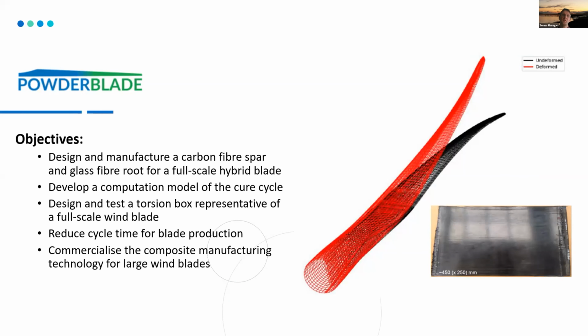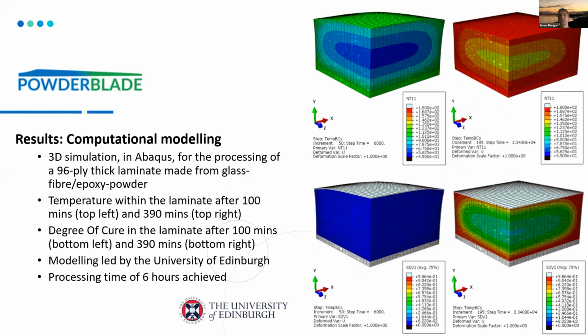The first thing was to design and manufacture carbon fiber spar caps and blade root section, to develop a computational model for the cure cycle, design and test a torsion box to reduce cycle time for blade production, and commercialize the powder epoxy technology. So a lot of the work on the computational modeling was done by the University of Edinburgh in Professor Ó Brádaigh's group. And they used Abaqus to make models of very thick laminate sections, so 96 plies and about 15 centimeters thick, and then looked at just how the material heats up.